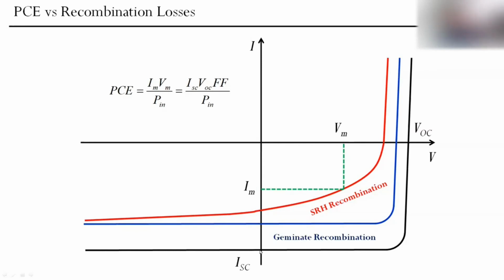We generate the same amount of excitons, and then we reduce one because of geminate recombination. They are not split and don't contribute to free charge carriers. But then we have the same amount of free charge carriers as here for this blue line, but with an additional mechanism of recombination, we lose more. So we don't generate more, but we lose more. That's why we lose in current, we lose in VOC, and also we lose in fill factor.